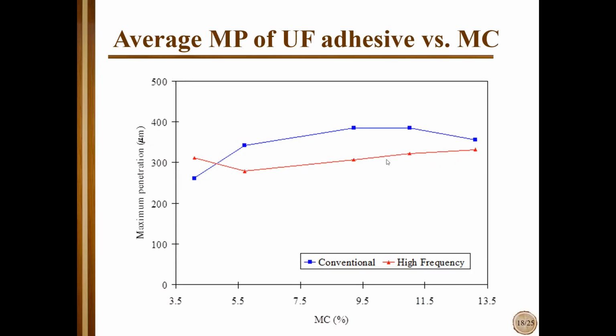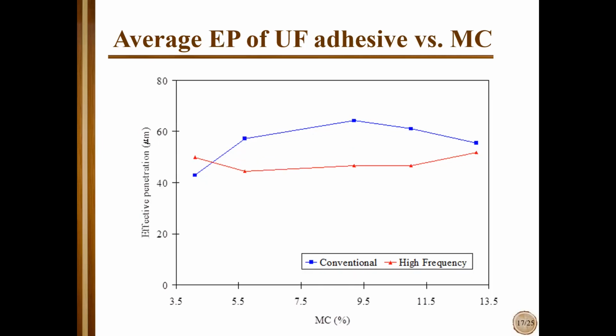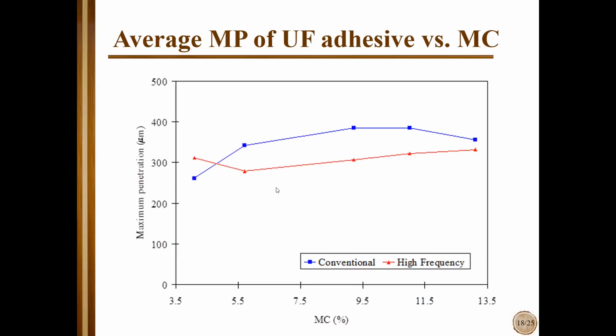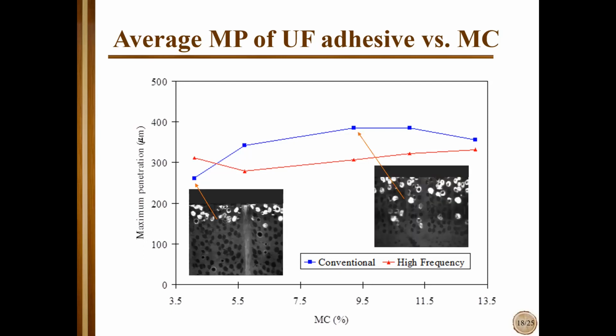The same results we got in terms of maximal penetration, only the scale is different. So here we have like 40 to 60 micrometers. Here it's around 300 micrometers. But the relation in regard to moisture content is practically the same. Also in some photos, you see visually that there are big differences in the penetration into each wood. So here just a few cells, a few lumens, but here maybe 5, 6 lumens in depth.